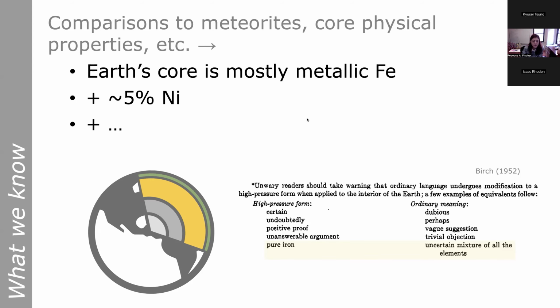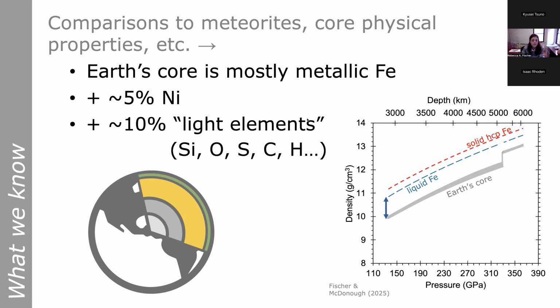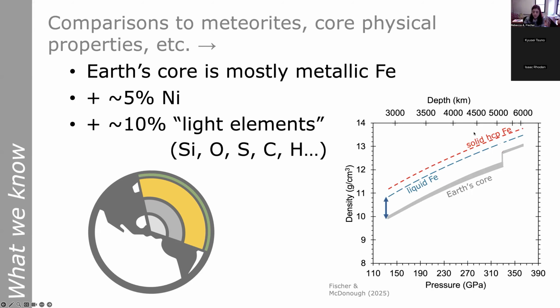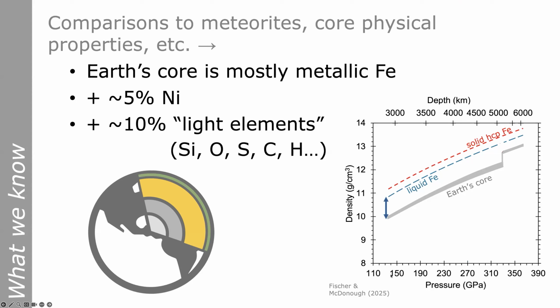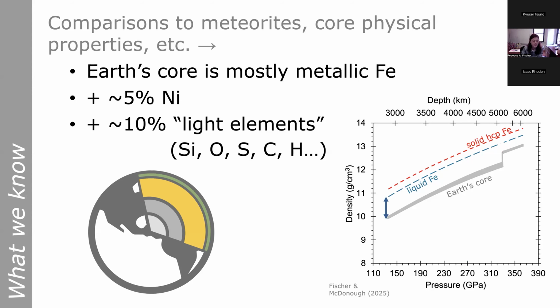And so in this talk, I'm going to be focusing on the roughly 10% of so-called light elements. Today, I'm going to be specifically focusing on silicon, oxygen, sulfur, carbon, and hydrogen. And this figure shows just one example of the evidence we have for these light elements being in the core. We're going to come back to this figure in a few slides, but this is showing density as a function of pressure or depth within the Earth over the range of the Earth's core. So the gray region here is the density structure of the Earth's core from seismology. And you can see the density of pure iron is in the right ballpark to match the core, but the core is a bit less dense. And that's one way we know that these light elements are in there.